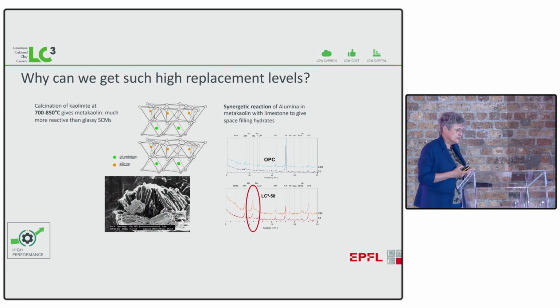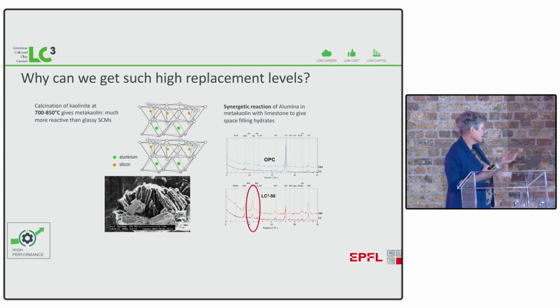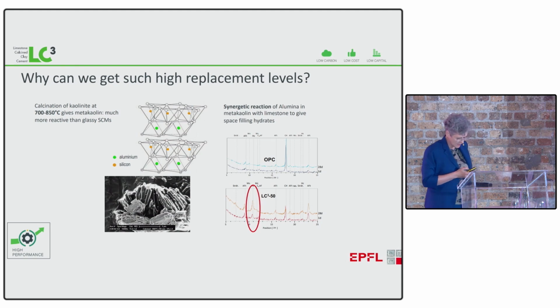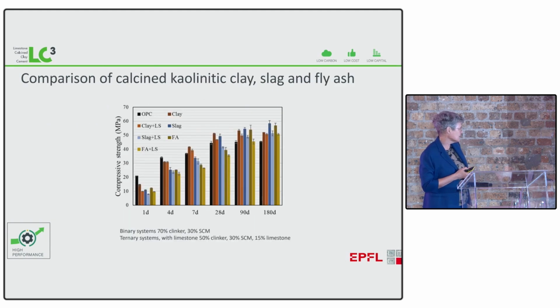Now, the essential point is, why can we get such high levels of replacement? And it's all to do with the presence of kaolin. So kaolin has this atomistic structure, which I've drawn here, where we have one layer of alumina, one layer of silica. The silica can react in the classic pozzolanic reaction, but the alumina also reacts with the limestone, and this is where you get this synergetic reaction, producing those peaks I've circled in red, which are mono and hemicarboaluminate. They're already present in limestone cement, so they're not something new. We know exactly how they behave, but we produce more of them in LC2 or an LC3 mix.